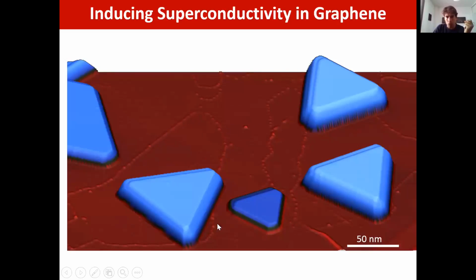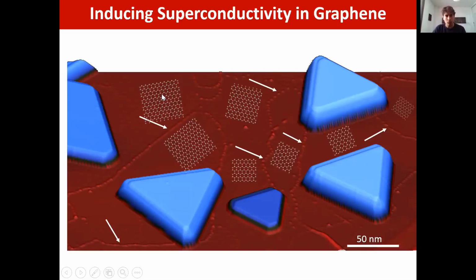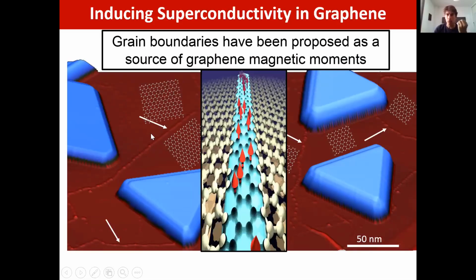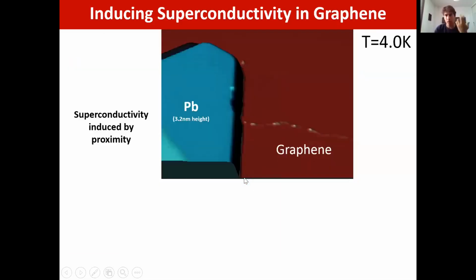So if now you take a close look at the image, you see some kinds of line defects on graphene. Here I point them with arrows. Let me explain what those line defects are. In the graphene layers that we have, there is simultaneous growth of different domains with different orientations. So when those different domains meet, when you have the formation of the complete layer, you have what is called a grain boundary. In this grain boundary, graphene with different orientations meets, you have many undercoordinated carbon atoms, and you have the formation of a grain boundary. And it is expected that on grain boundaries, you should have localized magnetic moments. That's what one expects from theory and some experimental indications.